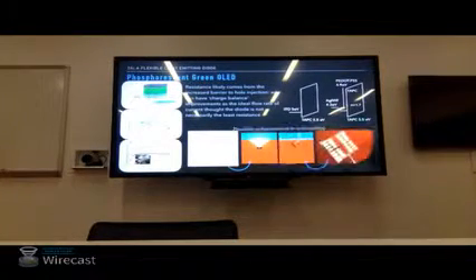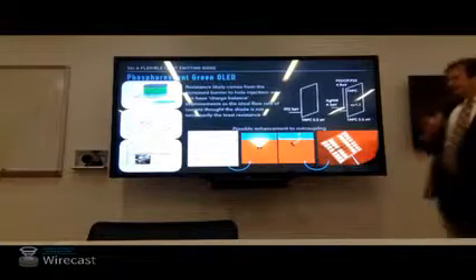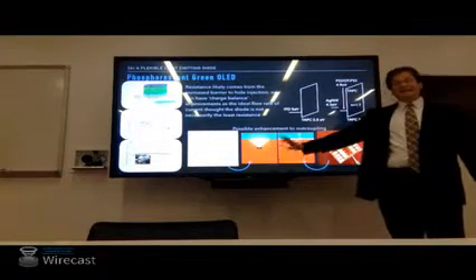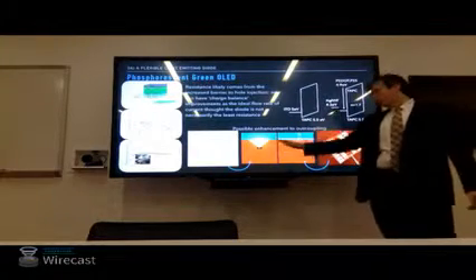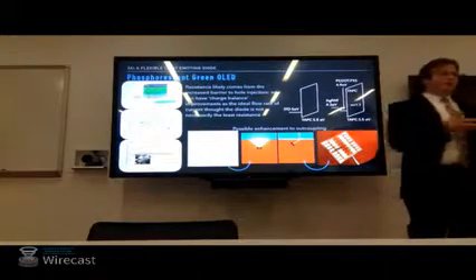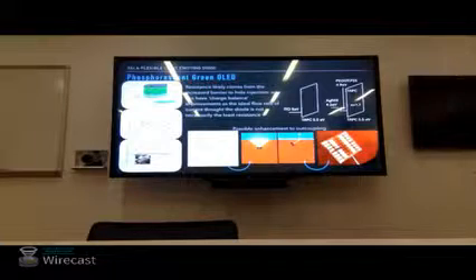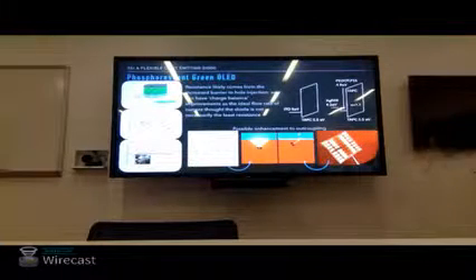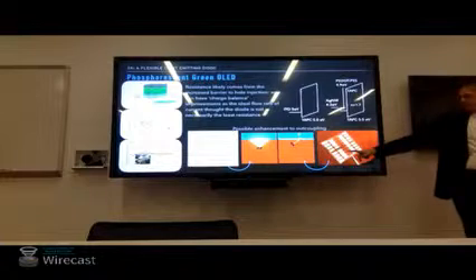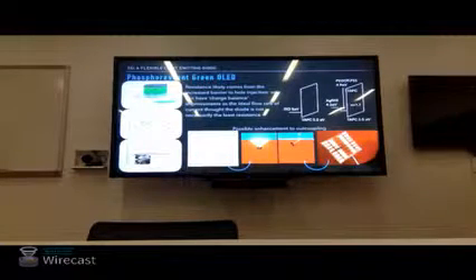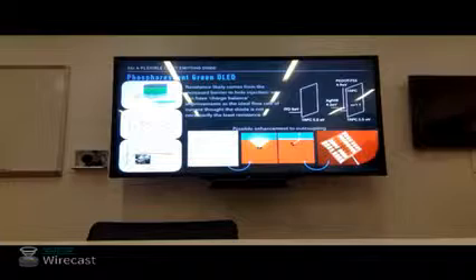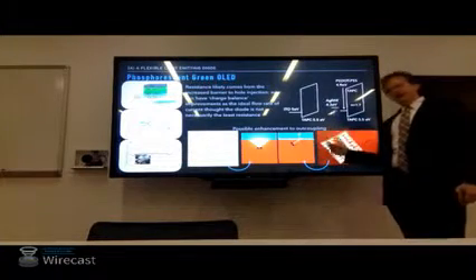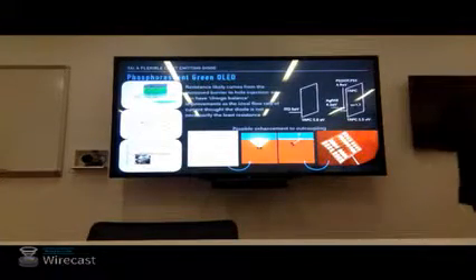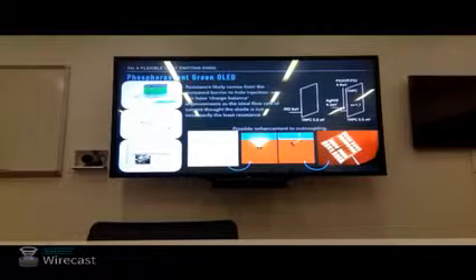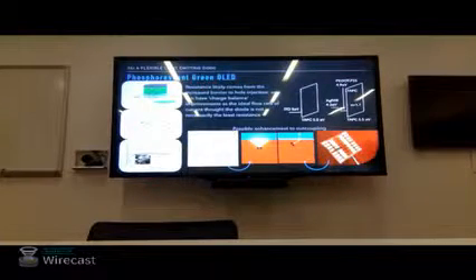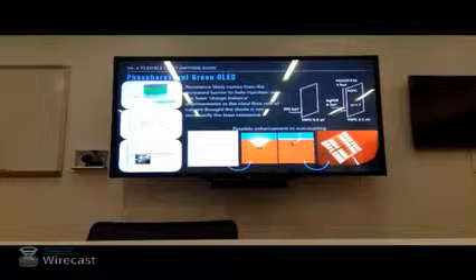Another area of enhancement is that this problem we discussed, the outcoupling, and not into a wave-guided mode, certainly holds for our planar interfaces when we use ITO. When we have nanowires here, the reason you can see where the nanowires are here is because they're hazy, they're scattering, they're a physical structure there. And now we have a chance to recover light if it hits this interface, even at an angle which should be wave-guided, because we don't have a nice interface anymore. We can have a scattering event which can help us recover that light.